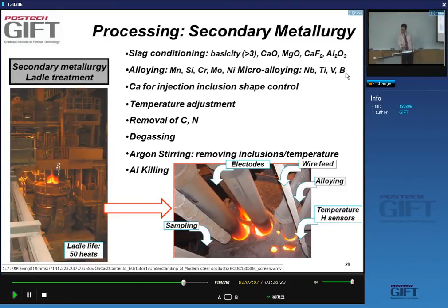Usually these are added not as pure elements. So you don't add manganese as pure manganese. You usually add them as ferroalloys, so alloys of iron and manganese, or iron and chromium. The reason is it costs much less to add a very high chromium iron alloy than to add pure chromium, okay? You also add calcium. Calcium is added to influence the shape of the oxide inclusions that you are not able to extract from the molten bath.